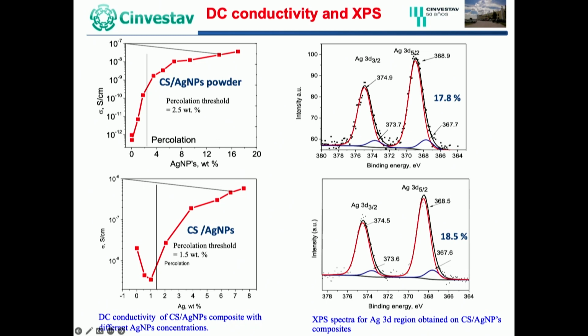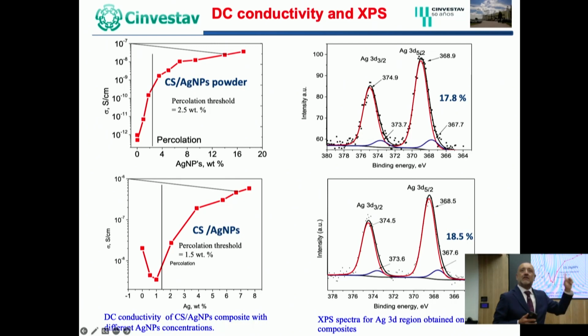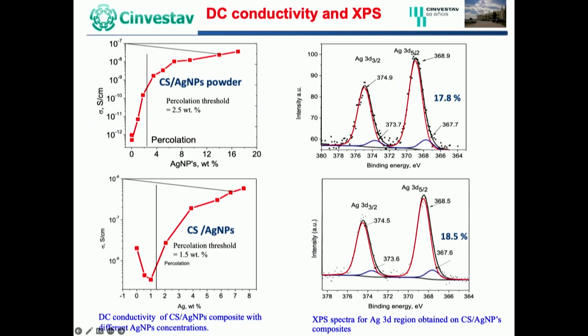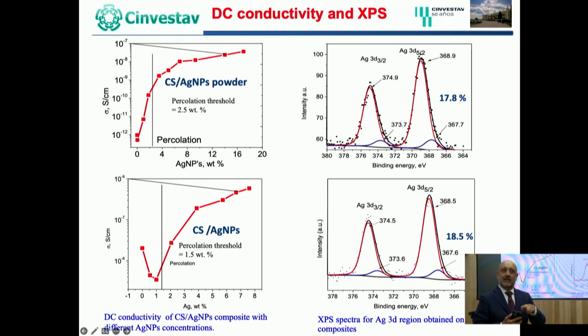And basically what we're trying to achieve is that different synthesis methods are producing different kind of particles. You see that number on the two graphs on the right-hand side. That's XPS spectra. No need to explain in detail. Just look at the numbers. Those percentages are the ionic silver. If you use a strong reducing agent, you end up with 99% of metallic silver. In other words, that number will be 0.11 instead of around 18. That number reflects the amount of ionic silver, silver plus 1. So what we discover is not only percolation help us to design proper materials, but different synthesis methods are producing different particles. And we faced this in the hard way.